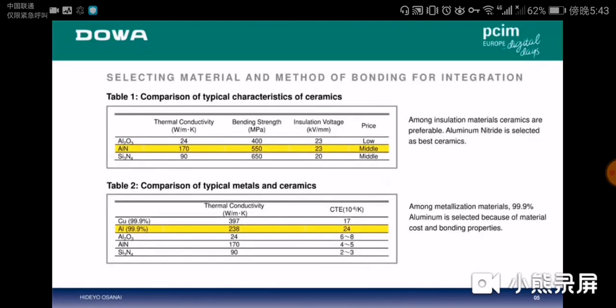When aiming for an integrated structure, we first examine the insulating materials and conductive materials. Insulating materials are typically resin, rubber, or ceramics, but ceramics are preferred in terms of thermal conductivity. Therefore, we selected aluminum nitride as the best ceramic. Next, among metallization materials, we selected 99.9% aluminum because of its material cost and bonding properties.